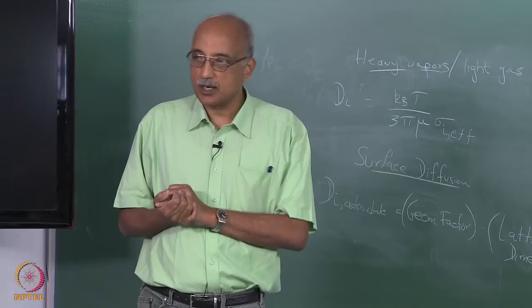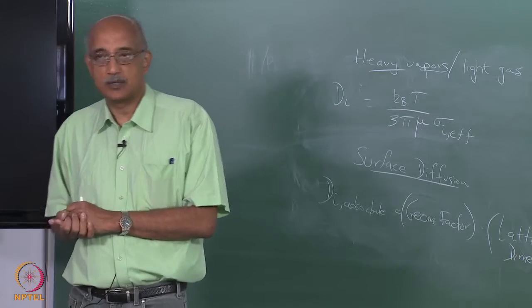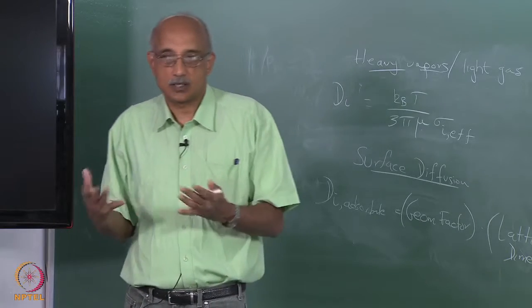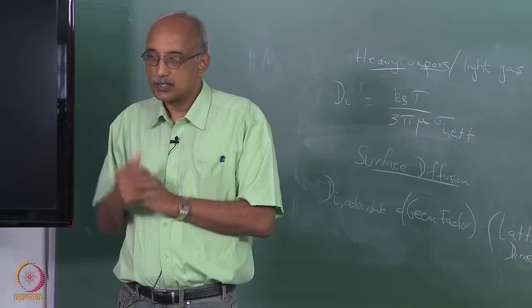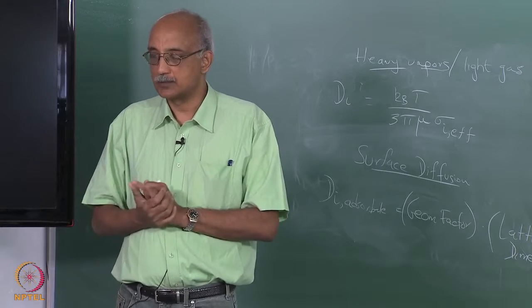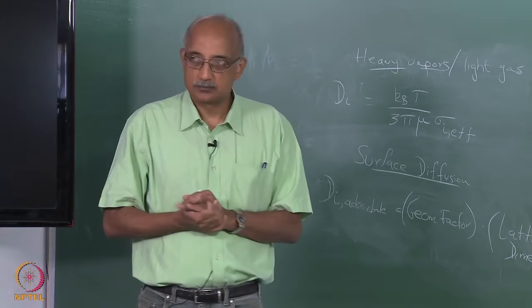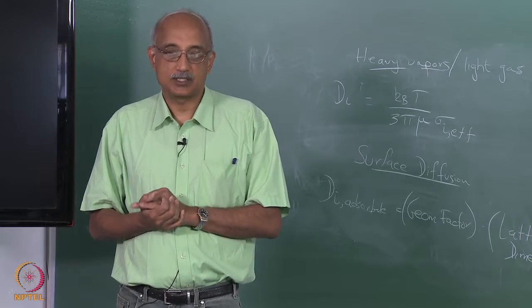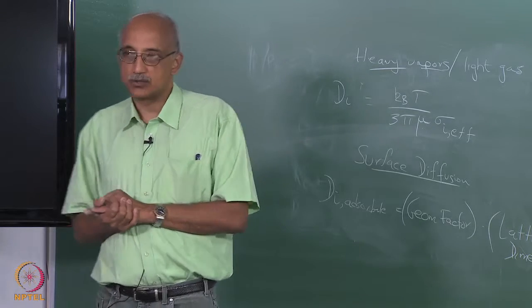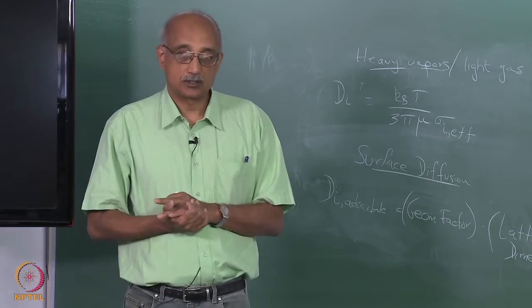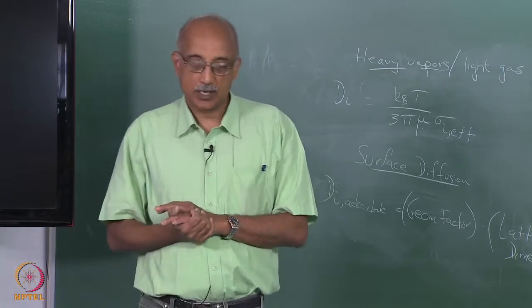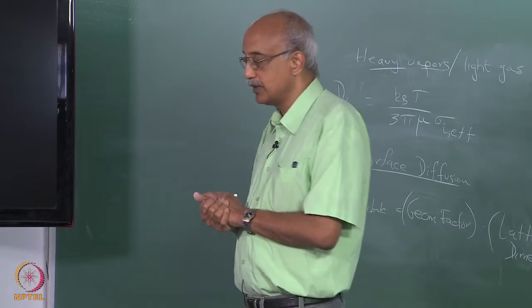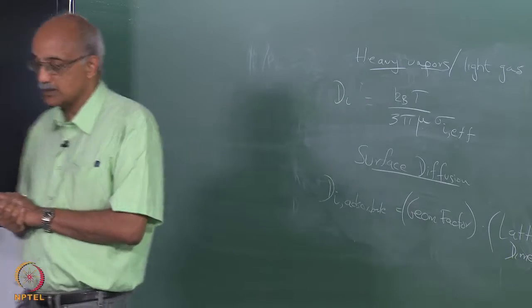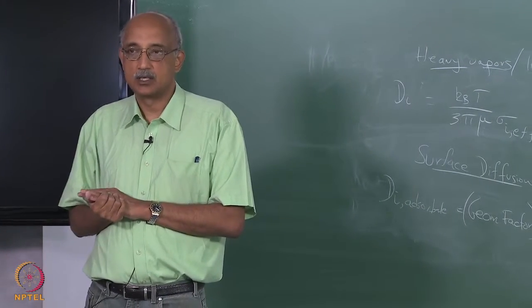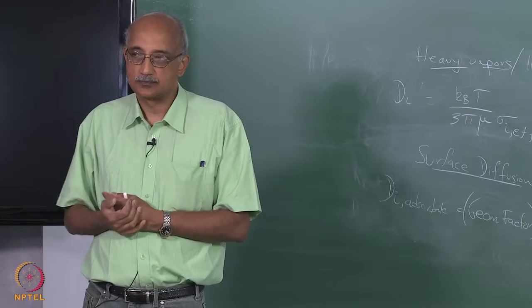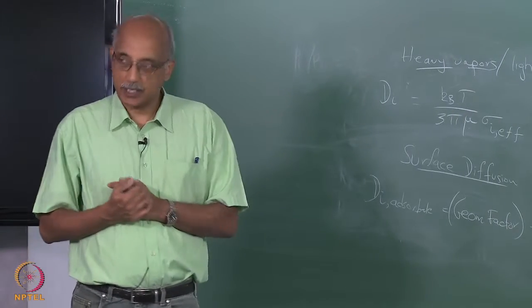Pressure is typically not hugely varying. The entire reactor will be set at a constant pressure, so there is no pressure-driven convection within the reactor. Magnetic fields, very rare. I'm not aware of too many CVD reactors which use magnetic fields to drive the process. However, electric fields are used, because it has been found that by setting up an electric field gradient, you can speed up a CVD process. And so, electrophoresis can be an important effect.